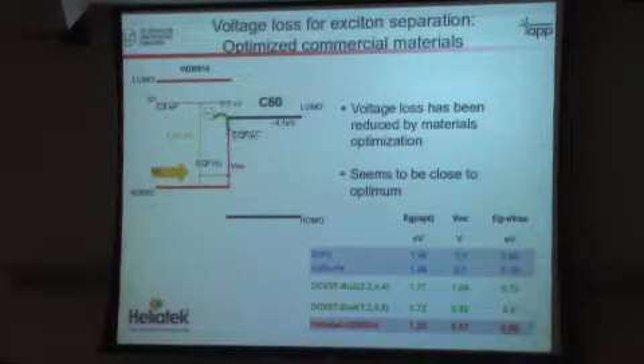I will not talk about voltages today, but I'm actually using one Heliatek slide here to show that for this most recent Heliatek material, which is again a proprietary thiophene derivative, the voltages are very good. Basically, what you want is a difference between optical gap and VOC which is as small as possible. And the Heliatek materials are now, actually, these are not really the best we have today. Today we are at about 0.6 volts between optical gap and VOC, and if you do some theoretical considerations, it looks like that is close to the optimum of what you can do in an organic solar cell. In an inorganic solar cell, you would have something like 0.3. That's what we lose in organics.